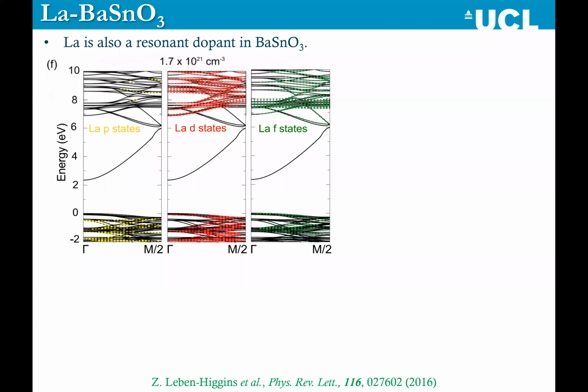And the last thing I will leave you with is the idea of this resonant dopant, as we call it, where you have this dopant state where it is resonant in the defect. The defect is resonant in the conduction band far away from the conduction band minimum. That is what we would call an energetic separation. But in the case of barium stannate, which is another new transparent conducting oxide, lanthanum dopes on the barium site, and the lanthanum states are very high above the bottom of the conduction band.